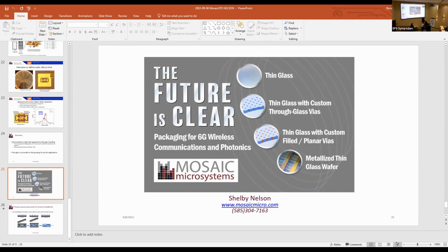So what we've seen with fused silica is if you have a 35 micron via in fused silica and you take it up hot enough, you can lose your hermeticity of the vias because the mismatch is even more. On the other hand, if you don't have to cycle up to 400 C, you may actually be fine, or if hermeticity is not your issue, you'll be fine. We haven't seen any cracking. With the Willow glass, we've actually taken filled vias, I guess 25 microns diameter, up to 450 C for 90 minutes, cycled it twice, no cracks, no change in hermeticity.